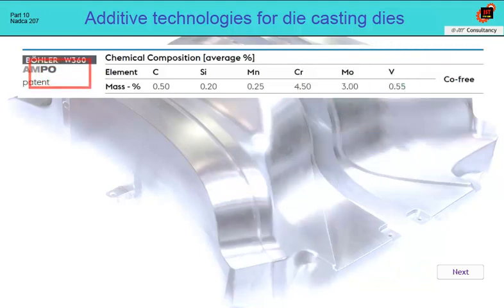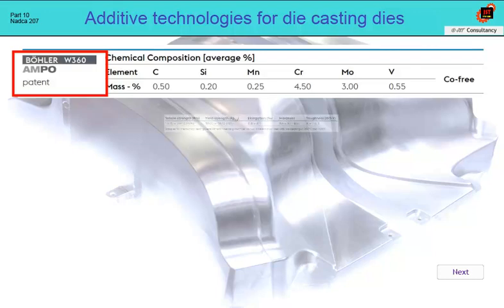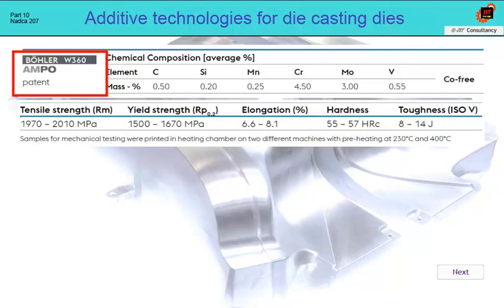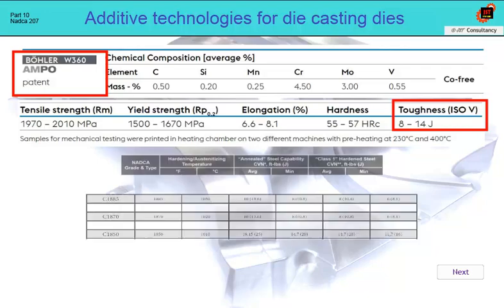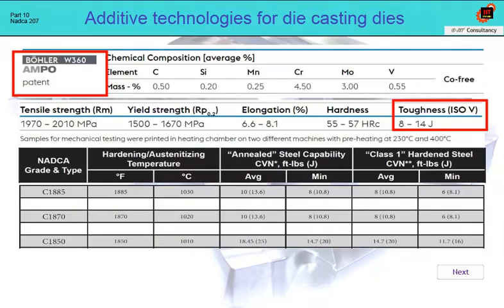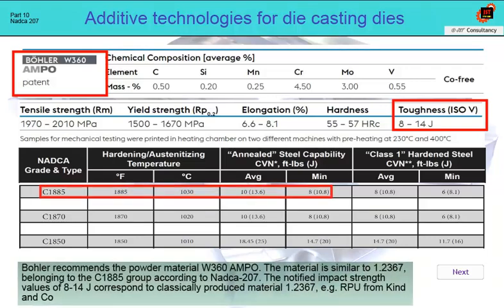This image shows the datasheet from Böhler Company for AMPO W360 powder. It is the first commercially published data for impact strength values on 3D printed parts. If we compare these values of 8 to 14 joules with the NADCA 207 values for the same type of steel, then these values are equivalent to the NADCA 207 recommendations. So the average value is 13.6 joules. The minimum is 10.8 for the test of steel capability.